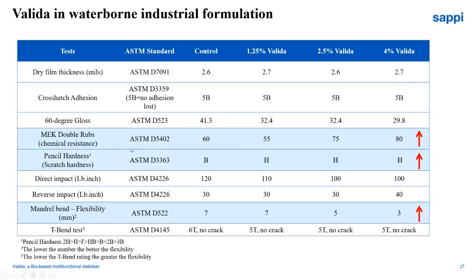The scratch hardness, measured by the pencil hardness, also improved. Here below the table you have the rating value, and we can see that the standard formulation has a value in terms of scratch hardness of B. When adding Valida, the scratch hardness improved up to a value of H. Also, at the same time, the flexibility improved. Here, the lower the value, the better is the flexibility. So we can see that the standard formulation, the reference formulation, has a value of 7, and the formulation including Valida shows a value of 3. So also here a very nice improvement in this regard, which can be really beneficial for industrial coating, for example.